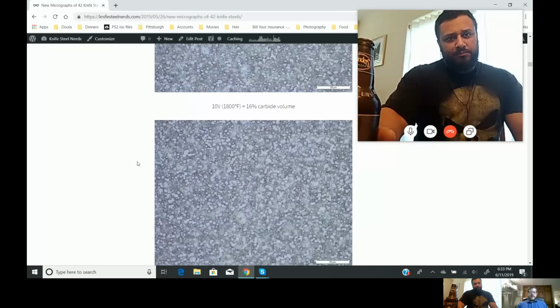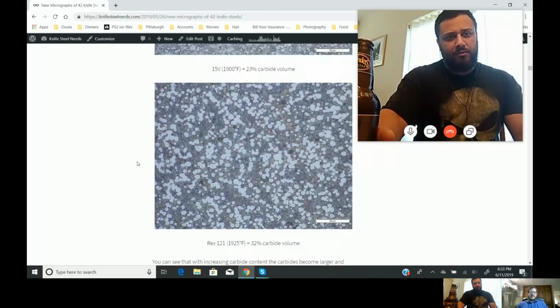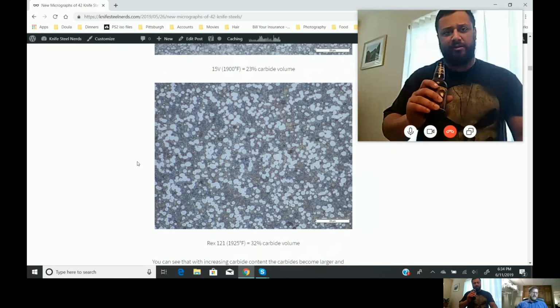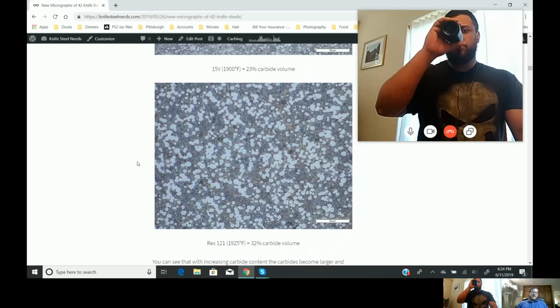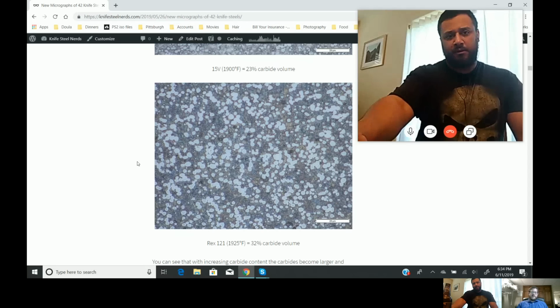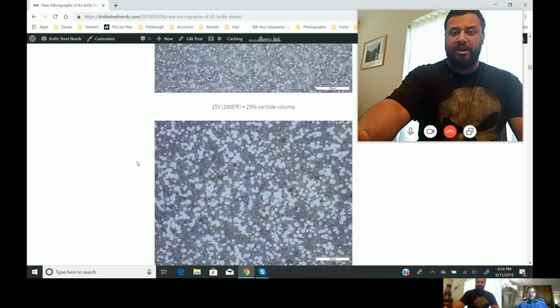And I think part of it might be that the Rex 121 has some of the high-speed steel carbides, which are like a moly tungsten carbide. Like an M6C carbide type? Okay. M6C. And the M stands for either molybdenum or tungsten or a little bit of iron. Okay. And those carbides will coarsen more readily. They're not bigger when the steel is atomized, but then they stick all the powder in the can under pressure at high temperature, and they grow easily at that high temperature. And so those carbides can get bigger than the vanadium carbides, which coarsen more slowly. So I think that's part of it.